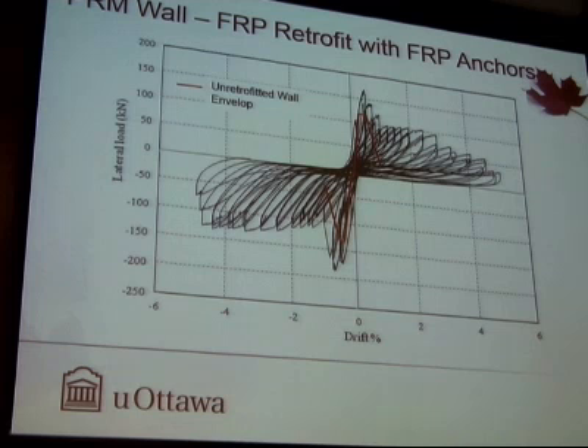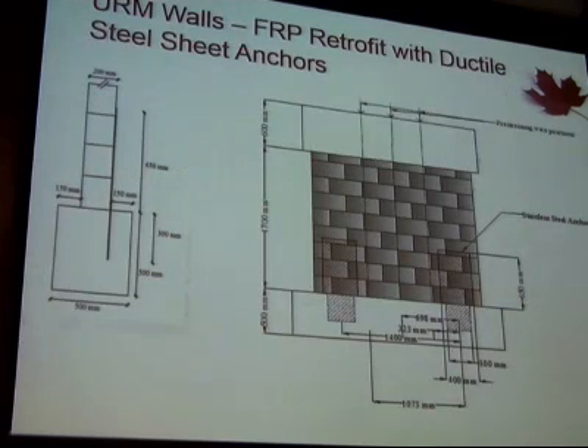diagonal strengthening was quite significant, and the red envelope curve indicates overall resistance in shear, whereas there has been quite a bit of improvement due to control of surface cracking. And finally, we combined use of FRP with ductile stainless steel plates.